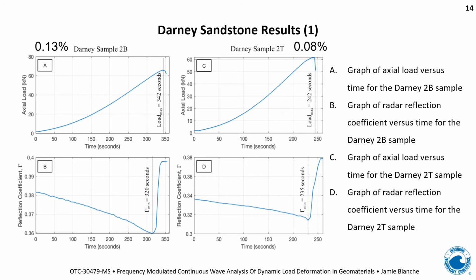Now the top left graph is talking about axial load. This is the incremental increase in load on the sample as a function of time. As you get to the peak of that graph, much like the graphs that we saw earlier on in the deformation theory section, the sample has failed. So the maximum load for this sample occurred at 342 seconds. But if we look at the reflection coefficient as acquired from bin 48, as shown in the previous slide, we're seeing a decrease in the reflection coefficient that troughs some 22 seconds before the fail point. In other words, the reflection coefficient decreases until it gets to a turning point in advance of the failure.